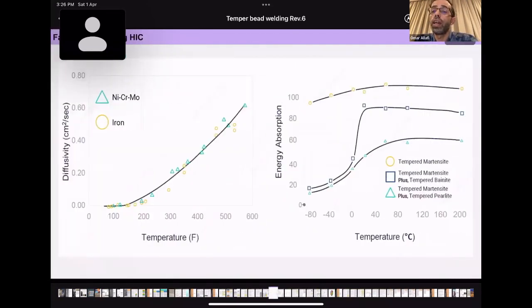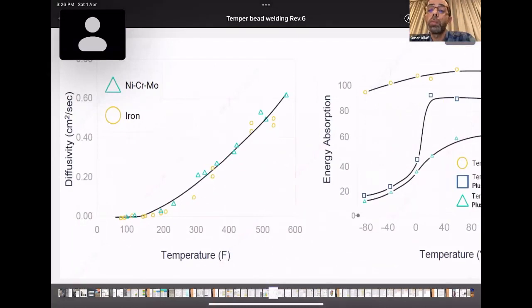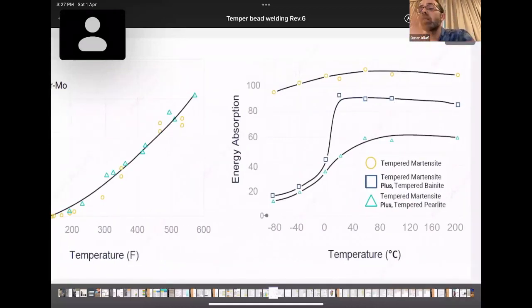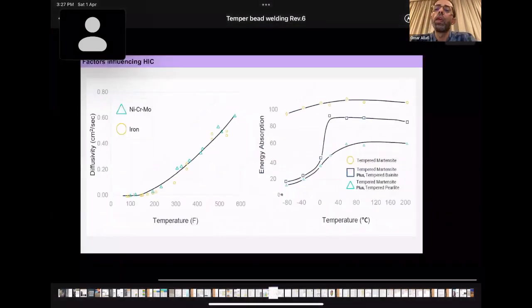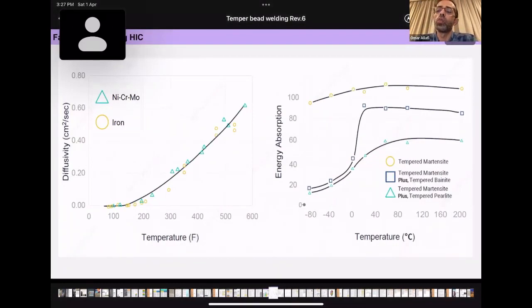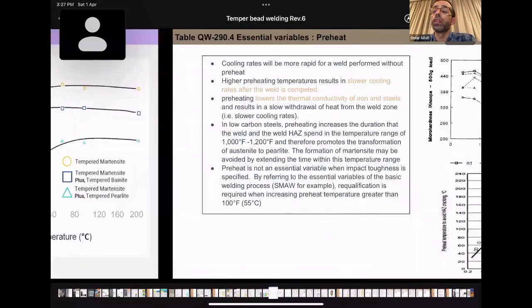hydrogen-induced cracking. And as we can see here in these charts, how temperature on this curve can affect the diffusivity of the hydrogen. The higher the temperature, the higher the diffusivity of hydrogen. And this is the temperature and toughness. This is for tempered material, but when the material is untempered, you will not have the same values. So this might also increase the chances to have hydrogen-induced cracking.